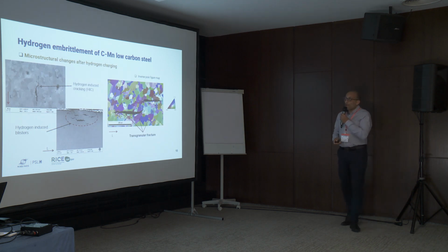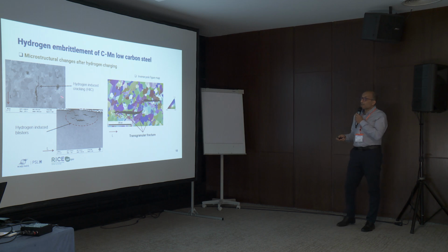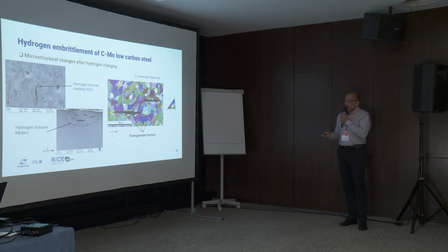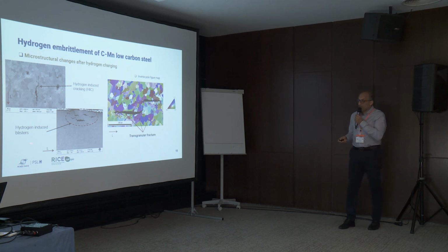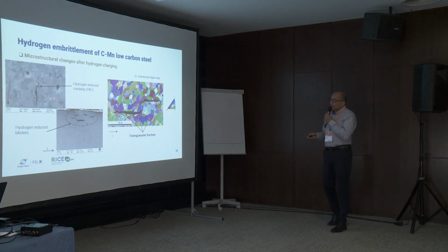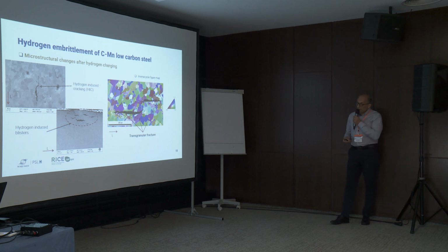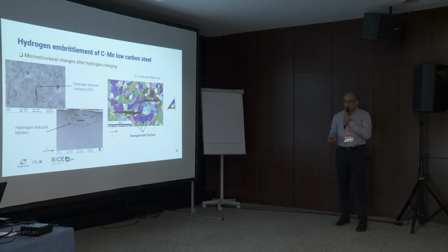After hydrogen charging, you have some degradation of the substrate. Here some hydrogen-induced cracking inside the specimen, cracks along the L direction, and some blisters at the free surface. The texture has been evaluated by EBSD, and you can see that the main crack mechanism is transgranular.